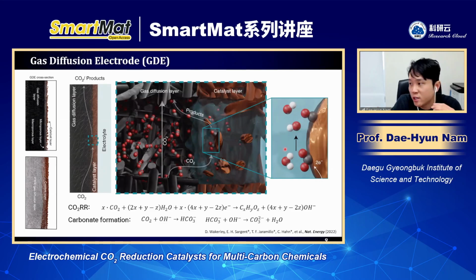Also, these days, what we are very interested in is how we can suppress carbonate formation. Because if we supply CO2 to this kind of GDE, some CO2 can participate in the CO2R, but others can also flow directly to the aqueous electrolyte. And if there is a lot of hydroxide, this will lead to the formation of carbonate. And this is the main reason for the lowered CO2 conversion efficiency. So it means that it is very important to design the catalyst, and it is very important to design the GDE structures to increase the CO2 conversion efficiency by suppressing this carbonate formation.